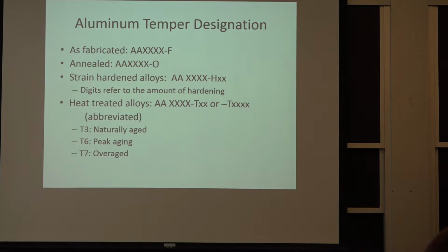In other words, at ambient temperature, they will age and become harder. There's going to be a dispersion of precipitate forming, and to delay that, you keep them in the freezer. You install them, and just the strain of deforming activates this transformation of forming precipitate. So within an hour after installing the rivet, it could be as much as twice as strong in terms of yield strength than beforehand.